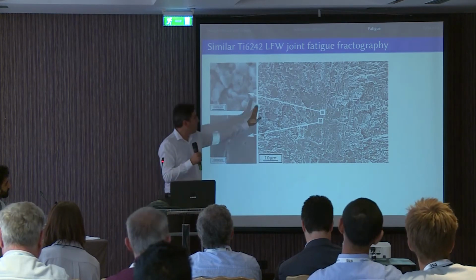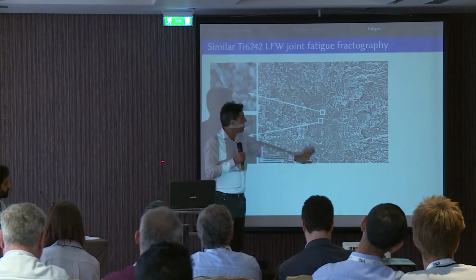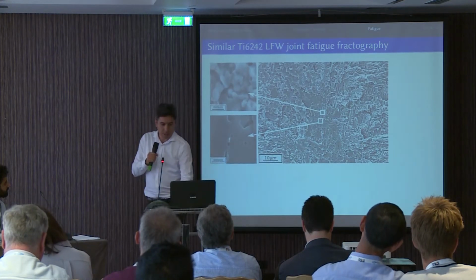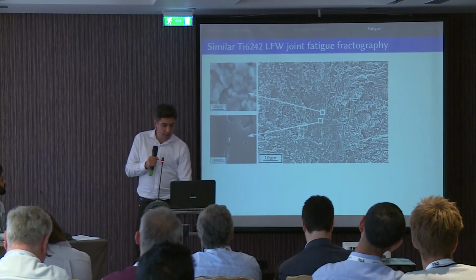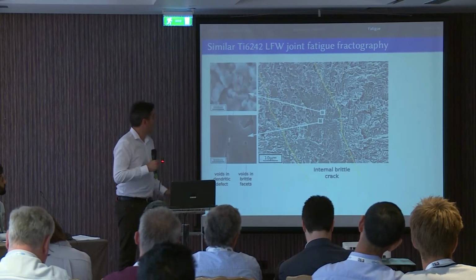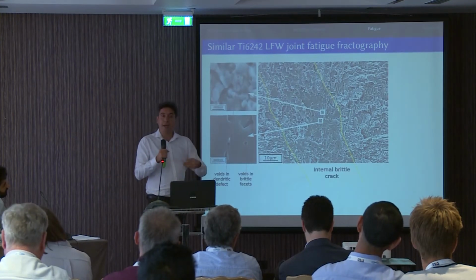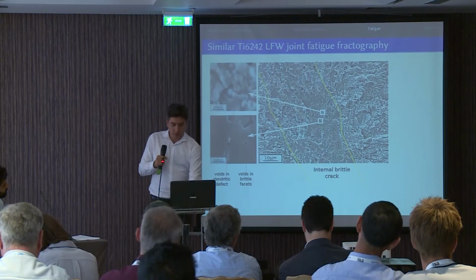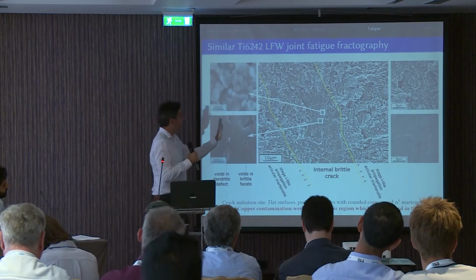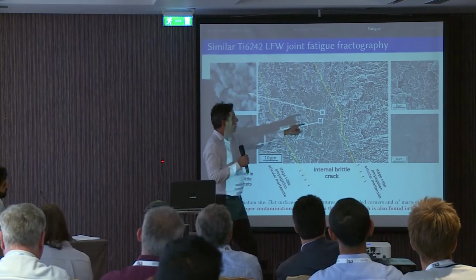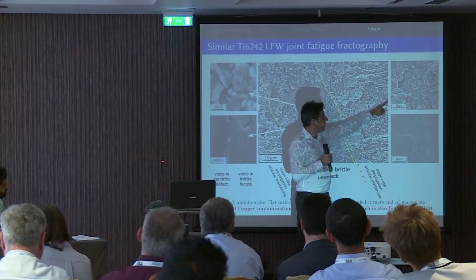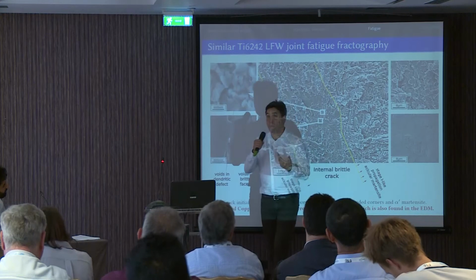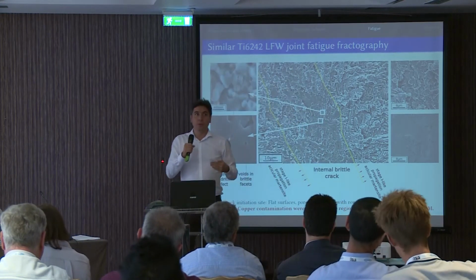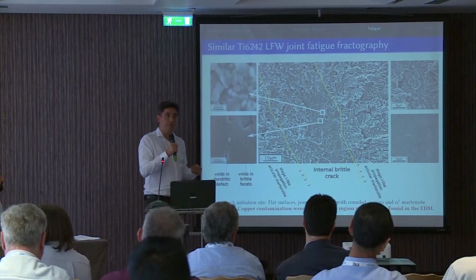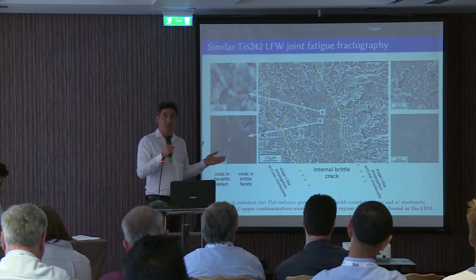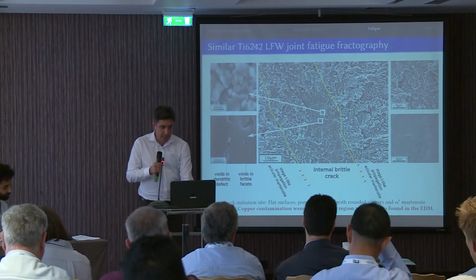So we have a very flat surface in the surroundings of this dendritic defect. So we can imagine that we have an internal crack. And if you look at both sides of this internal crack, we can recognize here the shape of the microstructure morphology. So we are in the presence of a crystallographic propagation. This is the stage 1-like fatigue crack propagation.